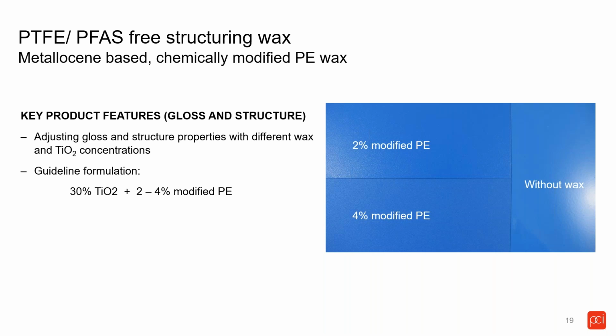Here's a couple other photos of the same wax that I was just mentioning. Now with this wax itself, it has to be used with TiO2 to get that structuring, and you can play around with the dosage of the wax and also the dosage of the TiO2. We are working on developing waxes along this type, PTFE free for structuring and powder coatings, where you don't have to use TiO2. You can also use carbon black or other pigments as well. But this one we're talking about here, it really does require the TiO2 to get the best structuring benefits.